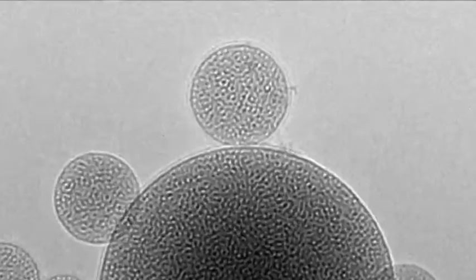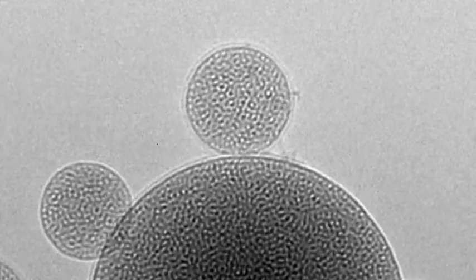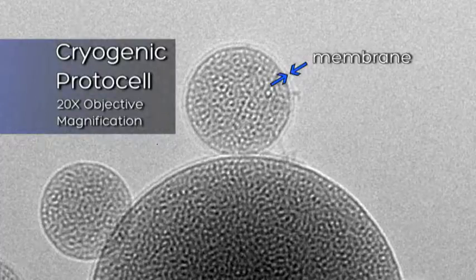And then once we form this sponge, we do something else that's pretty simple. We put on the outside of this sponge what's called a lipid bilayer. Every cell in your body is covered by this lipid bilayer. It's a very thin membrane, and we put that over top of this sponge. So we load the sponge with our drugs and put this membrane over it to keep the drugs in. And then on the surface of the membrane, we put molecules that recognize a particular cancer. So the particle is kind of stealth-like. On the outside, it doesn't get recognized by your body's immune system, but it has a few of these, what we call targeting ligands, that will recognize the cancer cell. So when it comes in contact, it will interact with that cancer cell and then go into it. And then we have the Trojan horse effect occur.